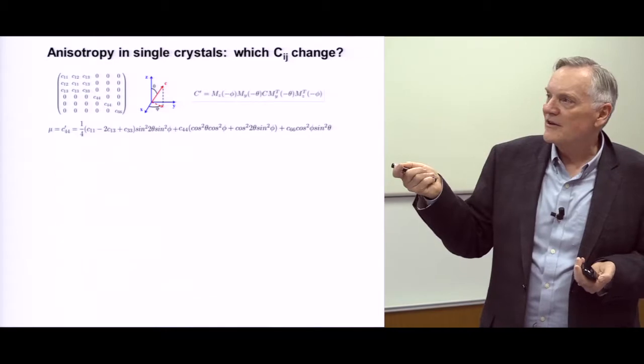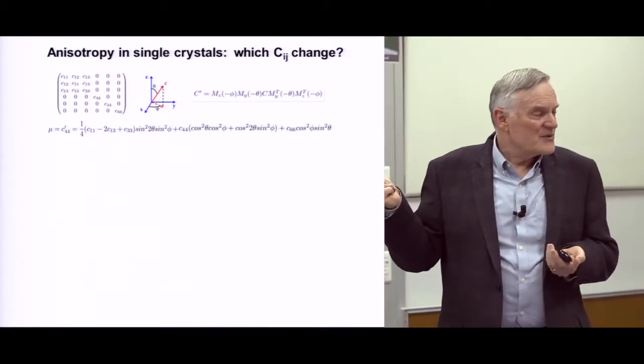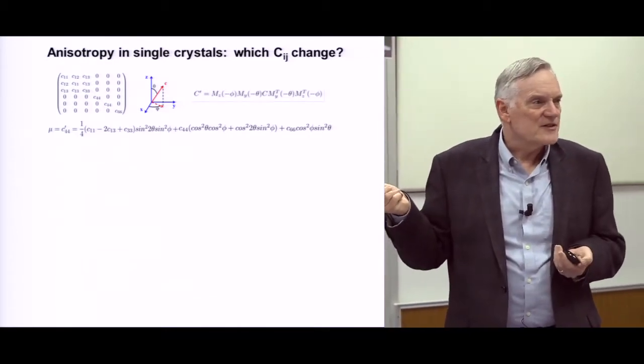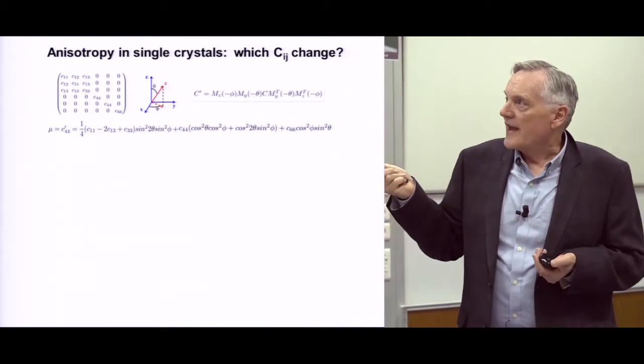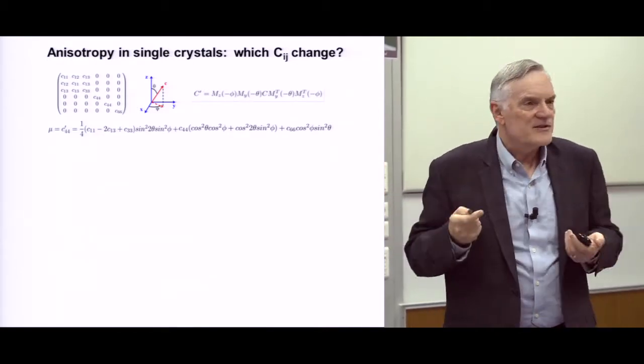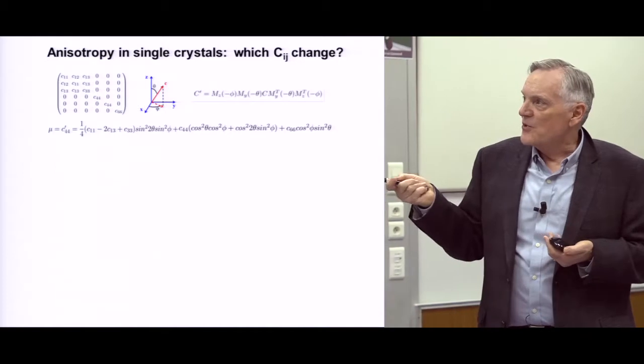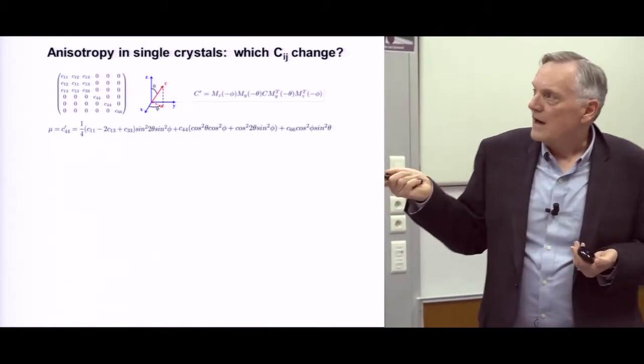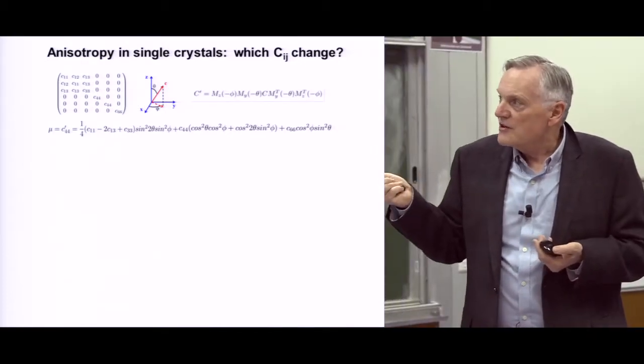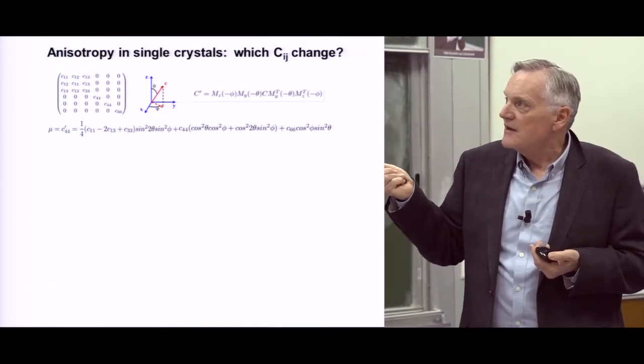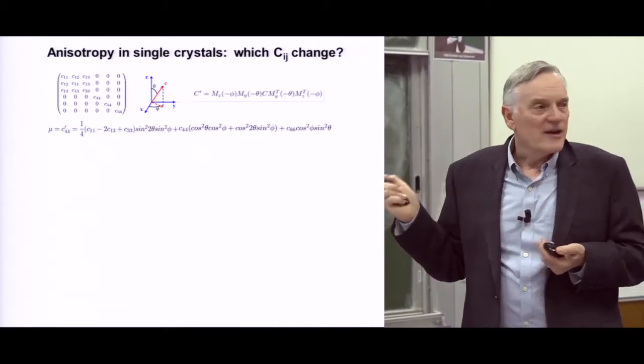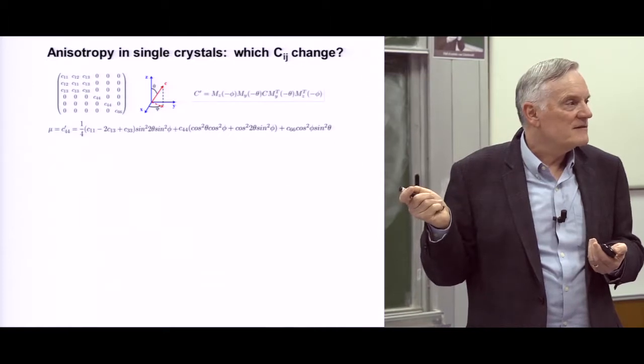And it's just algebra. It's the usual thing. You've got an elastic constant matrix with five separate elastic constants for a hexagonal crystal. You know the angle. You multiply a bunch of tensors. And you can write an expression, which you won't possibly read, but doesn't matter, that expresses the measured shear modulus in terms of these angles of the crystal and the five different elastic constants that this crystal must have.